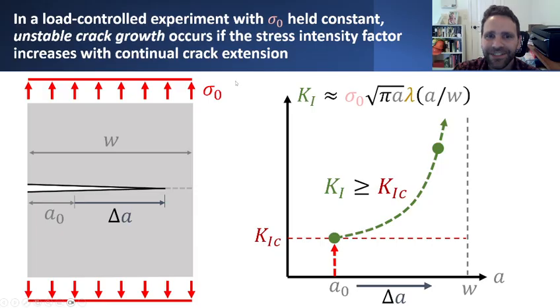But even if the crack extends just a little bit, just a tiny bit, if we say that our loading conditions are applied such that we're holding this external load sigma naught fixed, regardless of how the crack is extending or regardless of how the plate is kind of moving up, if we're doing a load control experiment, in other words, such that we're holding this external load fixed continuously, and we're trying to hold it there at the same value of sigma naught, then what'll happen is that the stress intensity factor will change.